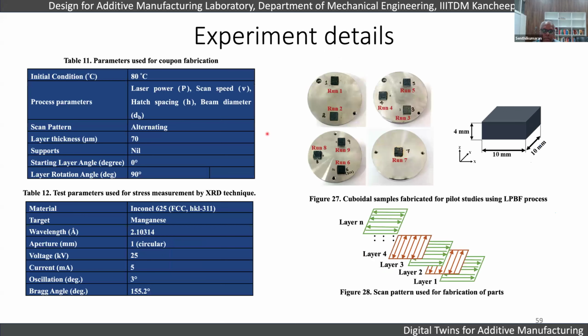And then we did the same mission, the same experimental plan, but with cubical specimens, using an alternate XY scanning strategy. This is used because it is known to cut down the residual stresses much better than scanning only parallel to the X or only parallel to the Y. So this is considered to be the best in terms of arresting the residual stresses.